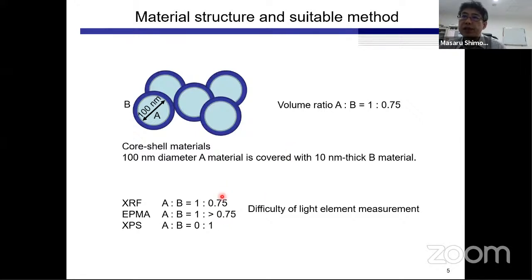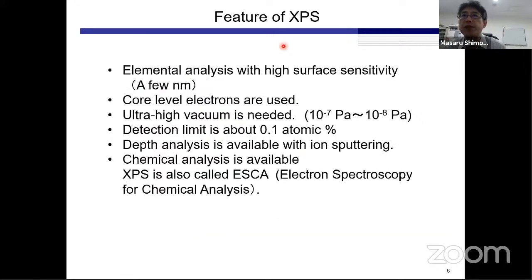So the surface sensitivity difference is the key point for elemental analysis. But in other words, XPS can select the information of the surface. That's also very important. And if we use the etching method, then we can etch the material. Then the elemental ratio of A to B changes. From that information, we can also guess the surface and bulk information of the materials. Like that, we always have to think about the escape depth of the information. This is becoming a key of XPS.